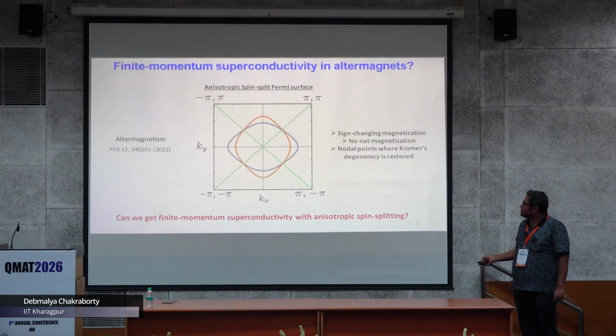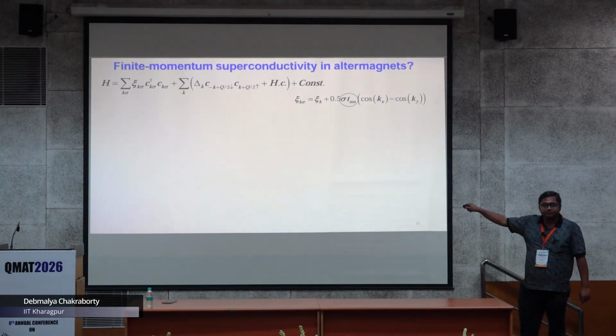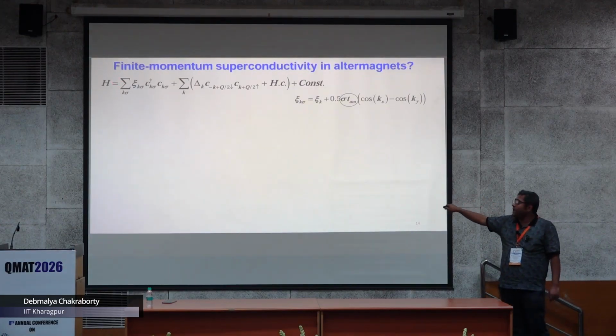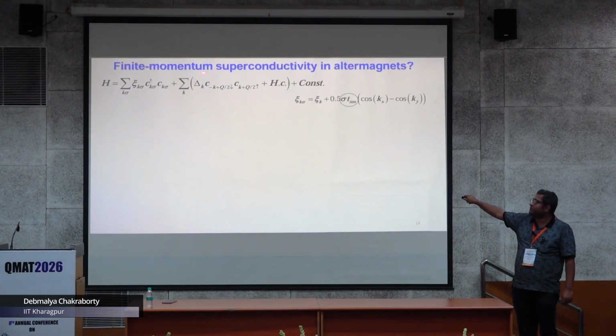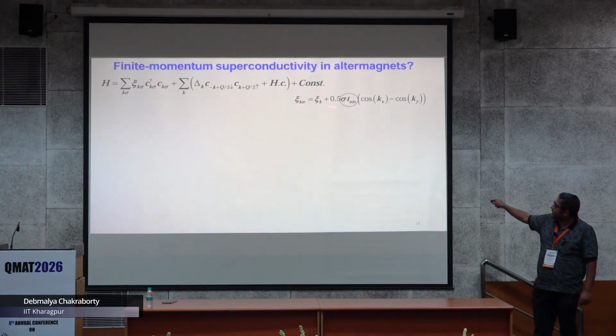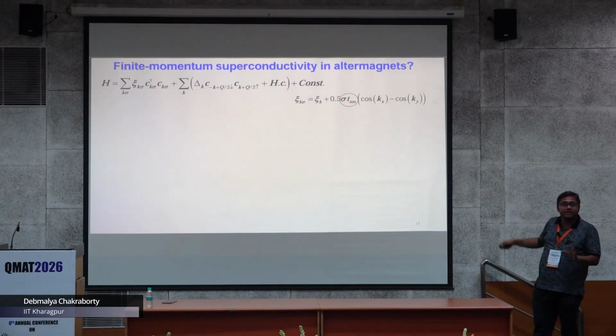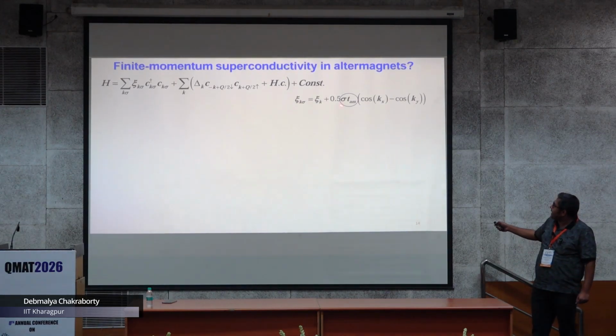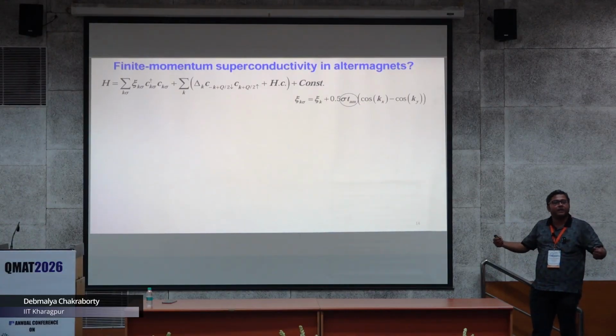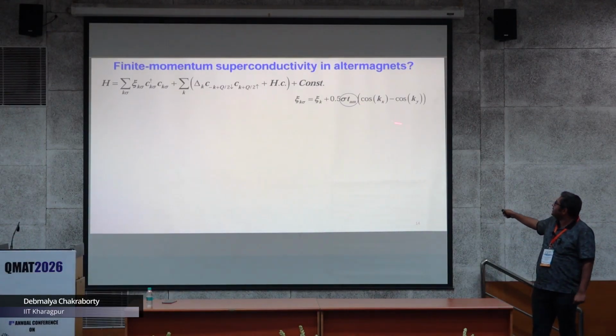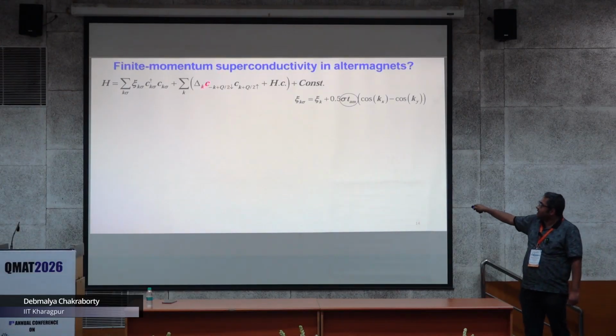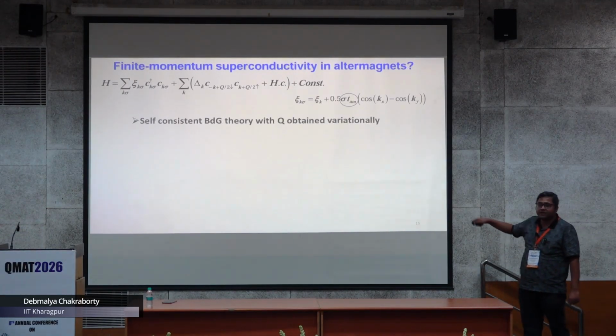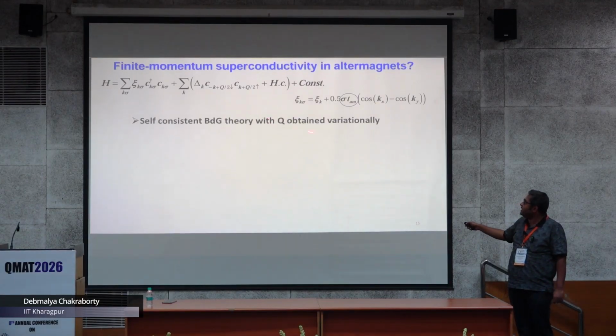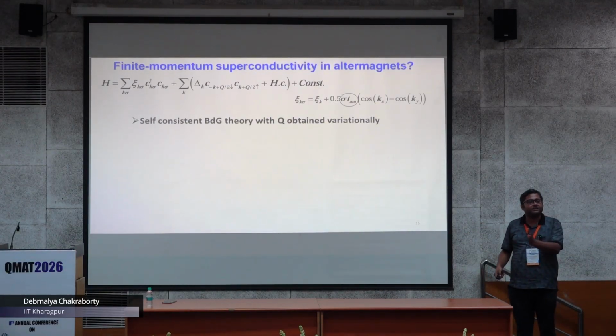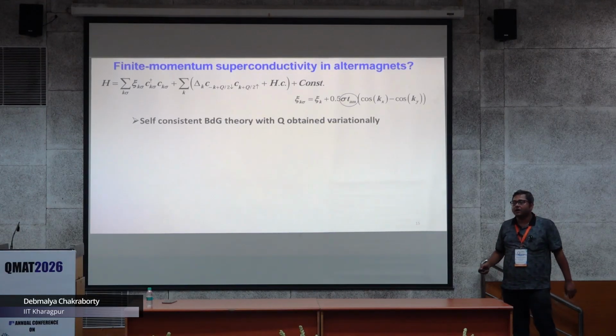To solve this question, what we did is start with the mean field Hamiltonian. We have a normal state, we have this pairing term which is given by delta q, and this normal state has a sigma times t_AM. This t_AM is the strength of the spin splitting. So if I have larger t_AM, my spin splitting would be larger, more altermagnetism, and we take it to be d_{x²-y²}, and then add superconductivity. We solve it self-consistently using Bogoliubov-de Gennes theory, and we treat q variationally. That means we check the free energy as a function of q and take the minimum q result.